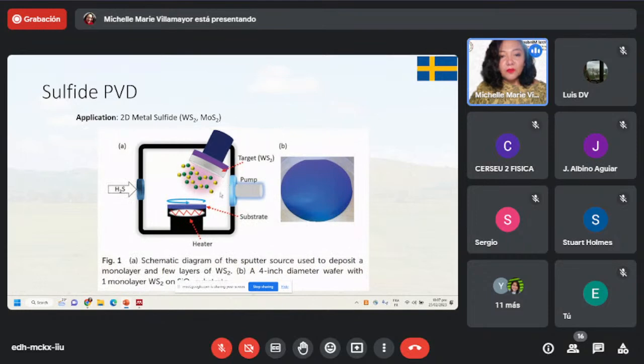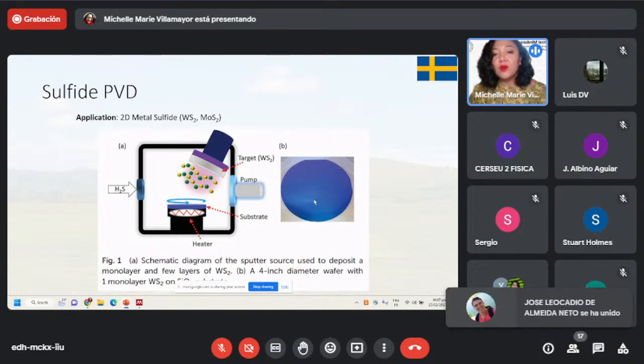So it's still magnetron sputtering. So we also have a target. There are magnets at the bottom, which we did not show anymore. The samples are heated at high temperature, up to 700 degrees Celsius. And we also introduced H2S and argon. So the sulfur here is the one that we use to help create the tungsten sulfide, even though our target is already tungsten disulfide. And as you can see, we have a very uniform deposit of this material onto our silicon substrate.